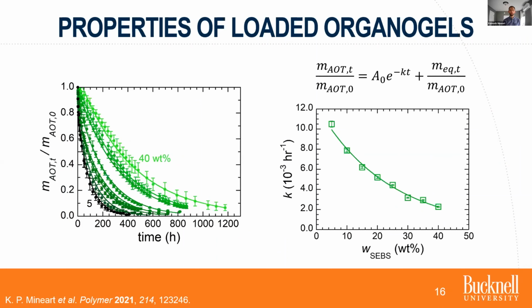But we can quantify these behaviors using a first order release model shown here. The primary thing I'll point your attention to is the first order release constant K, which describes the rate of release from these gels. And we see, as we observe on the left here, that the K value decreases as polymer concentration increases, suggesting that the release of AOT is slower with increasing polymer concentration.